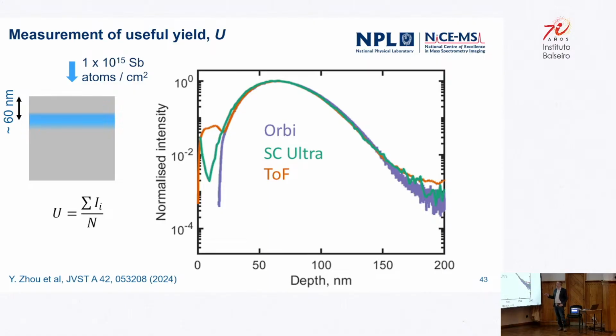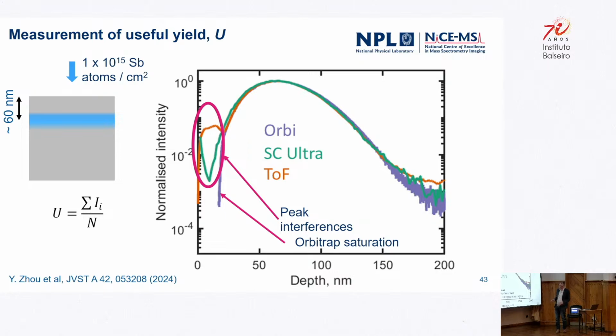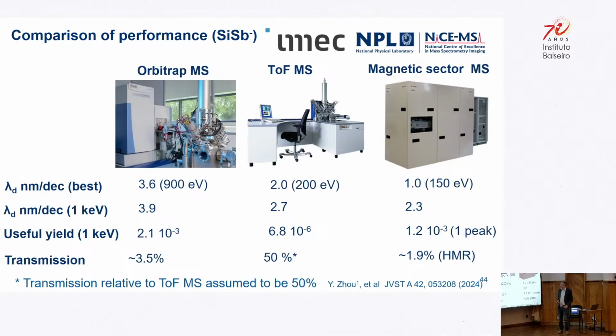And we compared our Orbitrap technique with a magnetic sector instrument and a time of flight analyzer. I don't really have time to go into the details, but basically, because we have such high mass resolution, we don't pick up some artifacts that you get from other techniques. But the key parameter here is something called the useful yield, and this is our OrbiSIMS, this is the TOF SIMS. I should say TOF SIMS is a brilliant technique, don't get me wrong, it's an amazing technique. This is a magnetic sector instrument that they use in the semiconductor industry, but the sensitivity of our instrument here is pretty much the same as these dedicated magnetic sector instruments because of the way our instrument works.